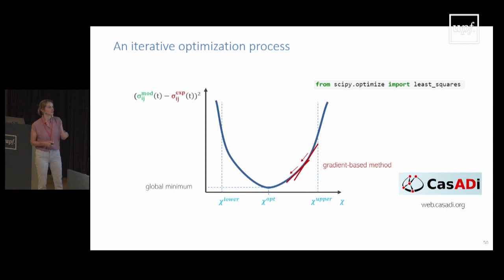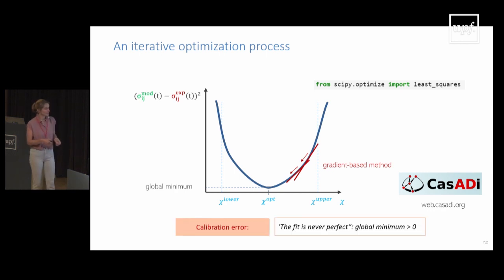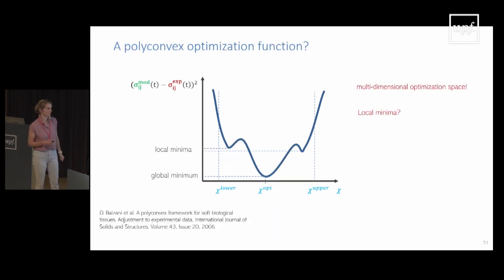But just for your information, this is a very nice toolbox that was also developed in collaboration with Leuven that helps you a lot to do proper optimization. But in any case, if your experimental data is not perfect, I think we established that, it means that your model will never be a perfect representation of your experimental data, which means that you will never have reached a global minimum that's perfectly zero. And this discrepancy between 0 and the actual residual value of your optimization is what we call the calibration error. And this is, again, something that needs to propagate into the model.